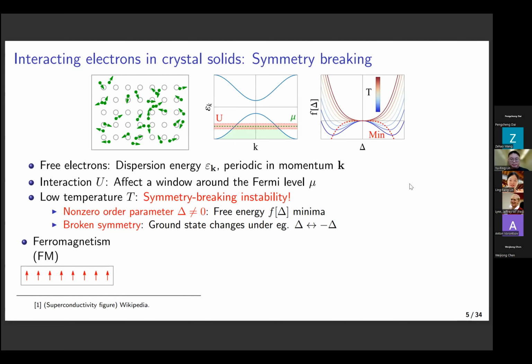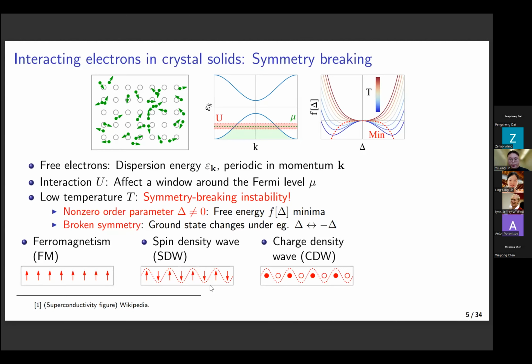For example, the most classic one will be ferromagnetism, where we can think of the order parameter as just the magnetization, and it breaks the spin rotation symmetry. And in addition to spin rotation symmetry, we can further break a translation symmetry in space so that we will have a spin density wave which modulates in space. And we can also just break the translation symmetry, and it will lead us to a charge density wave with charge density modulations in space. And also, if we break the particle number conservation, we have superconductivity.